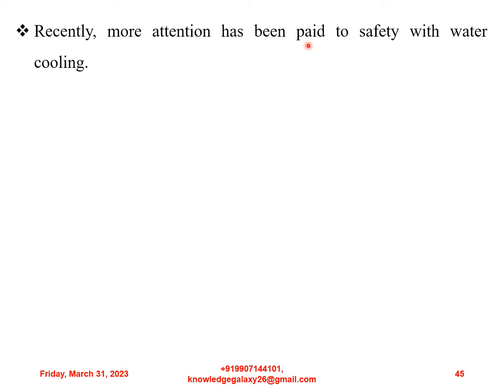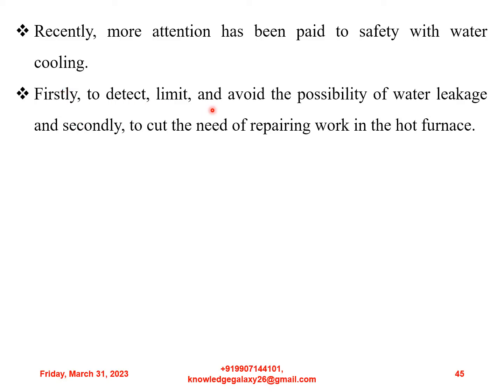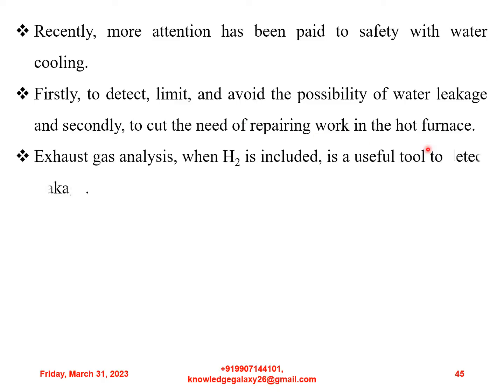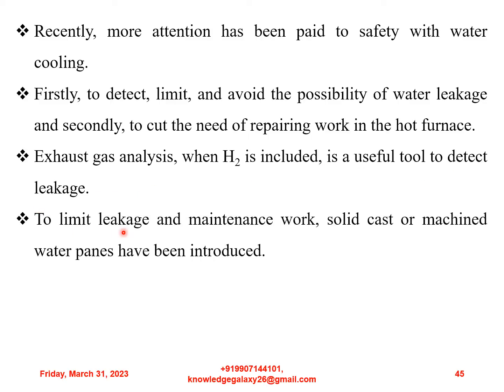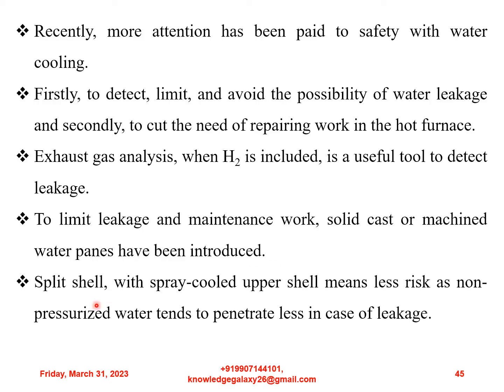Recently, more attention has been paid to safety with water cooling. Firstly, to detect, limit and avoid the possibility of water leakage, and secondly, to cut the need of repairing work in the hot furnace. Exhaust gas analysis, when hydrogen is included, is a useful tool to detect leakage. To limit leakage and maintenance work, solid cast or machined water pans have been introduced. Split shell with spray cooled upper shell means less risk, as non-pressurized water tends to penetrate less in case of leakage.